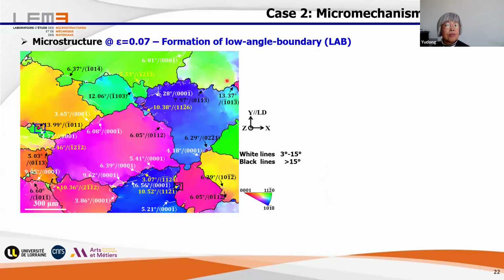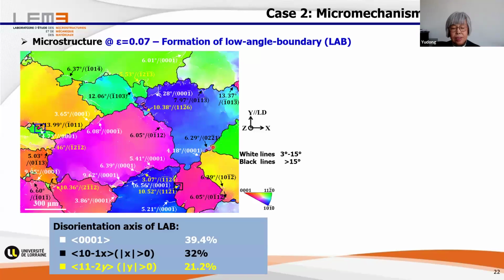When we increase the deformation to a true strain of 0.07, we see more bulgings happen, but we also see a lot of these white lines with angles between 3 and 15 degrees forming along the boundary area, enclosing the bulging part. Fengming made a very careful analysis over a large area, and then she made a statistical count, and she found that 40% of such boundaries have the rotation axis 001.